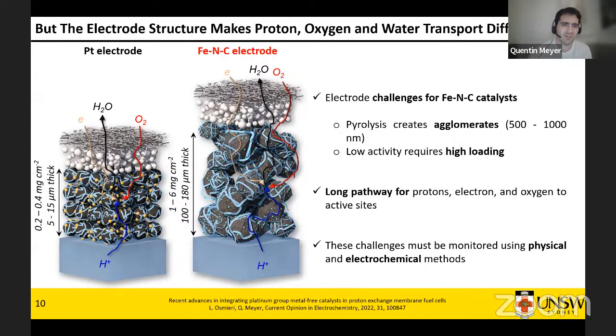And what I mean by optimized is the way your ink is prepared to put your electrode has been spent a lot of effort. The amount of ionomer, which is the material you can see in the circles here, has been very carefully optimized to get the best interaction. And typically, you get a loading between 0.2 and 0.4 milligrams per centimeter square, which is somewhere between 5 and 15 microns thick. In this kind of environment, proton transport is very easy because you're dealing with something very small.